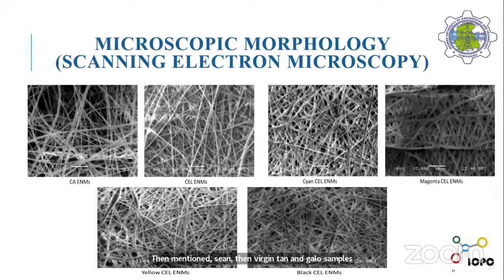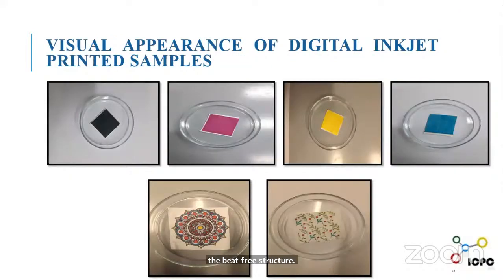These are the scanning electron microscopy images. The SEM results show that before, as cellulose acetate, and after being regenerated into cellulose fibers, there is no difference in the structure. We get a smooth, bead-free structure after printing and before printing. And these are the visual images of the printed samples of nanofibrous mats.